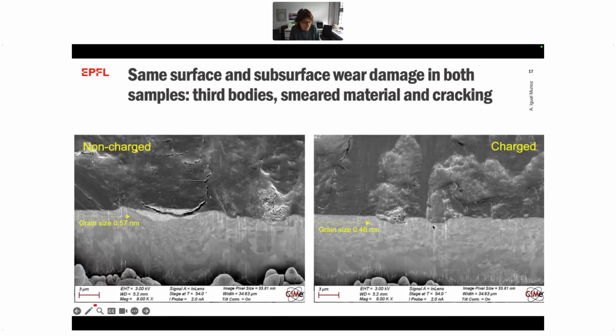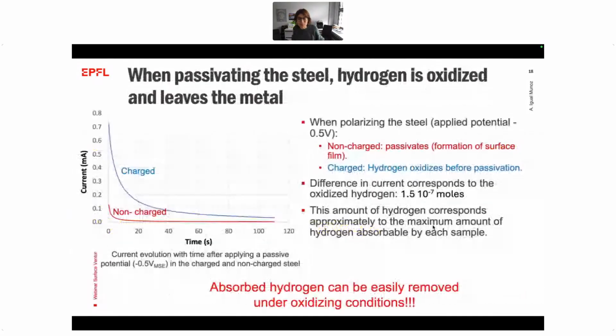So what has happened? Our question is, are we sure we have inside the hydrogen we have taken during the charging? And then to verify that, we did just again an extra test, imposing, when we want to passivate the steel, of course, we have to apply an anodic potential, a certain potential. And what happens is that we register the current at this potential.